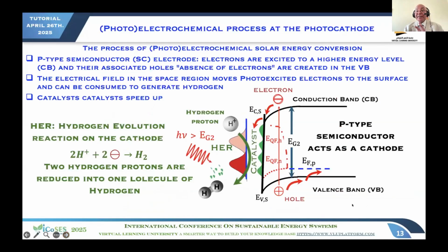Okay. I show you here exactly the same, but with a P-type material. In a P-type material, you have the Fermi level near the valence band. And when you excite with energy higher than the band gap, what happens? The holes now go to the bulk, not to the surface, and the electrons go to the surface, because the electrical field in this region near the surface is completely the opposite of the one for N-type. Therefore electrons will come here, will meet protons H+, and then make the reduction into hydrogen. And that's what's happening here.